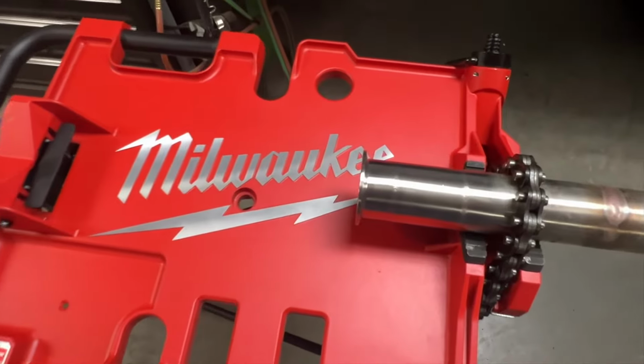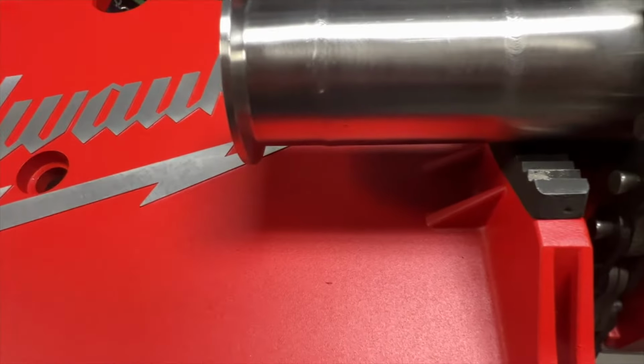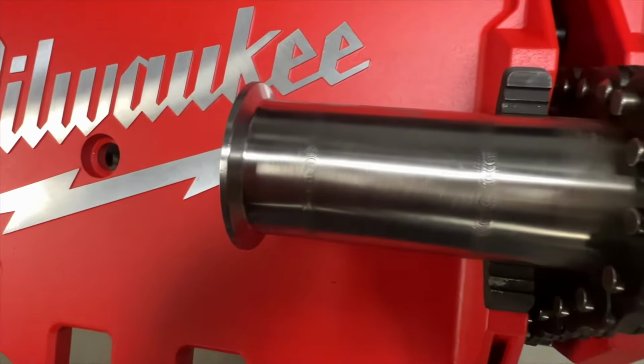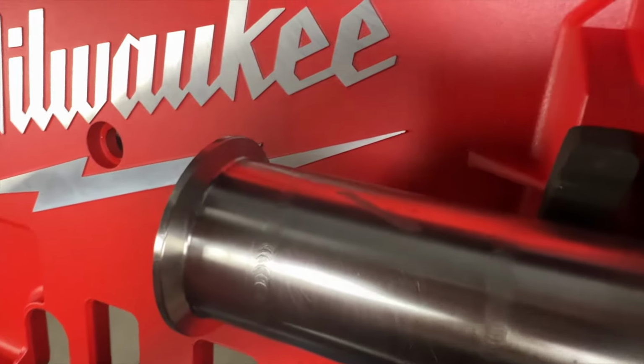When welding sanitary tubing, your purge pressure is critical. If it's too high, that weld's going to be pushed out or concave on the inside. If it's too low, however, it'll be sunk in. When welding pipe, purge pressure isn't quite as critical. You just want that root to be as clean as possible.